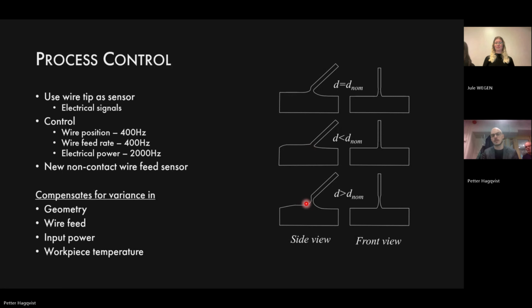There's also at the bottom another unwanted state, where the wire is positioned too high. This will typically lead to this very weak neck being broken, and then we get droplet transfer, which is not as detrimental as the middle one, but you would get an uneven surface and it might be harder to continue depositing. And when you don't have electrical contact between the wire and the melt pool, you're no longer transferring any electrical energy, so you lose a lot of power.